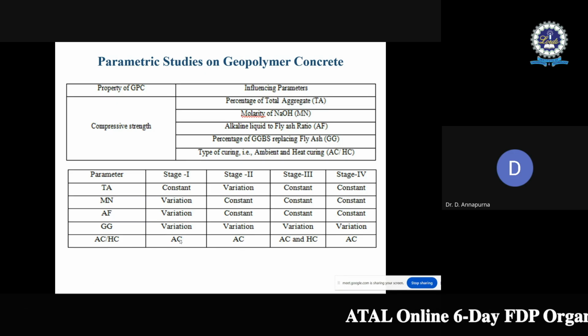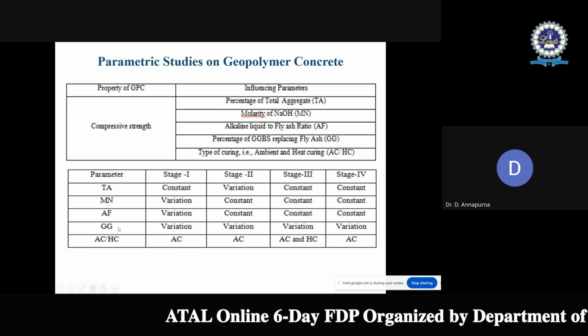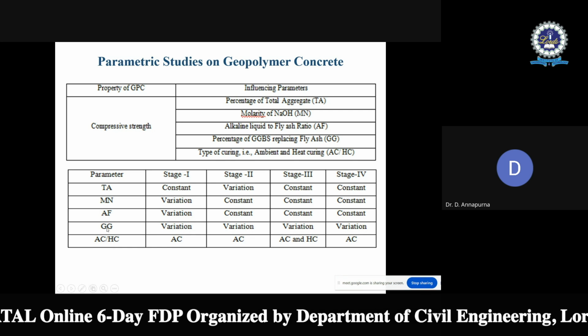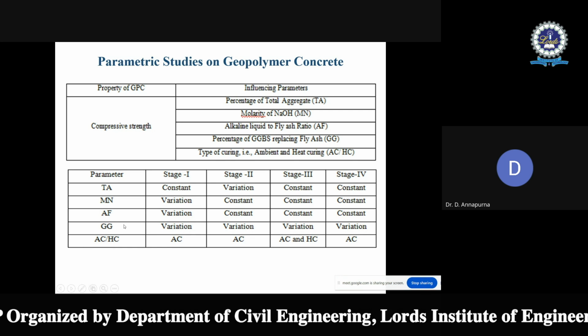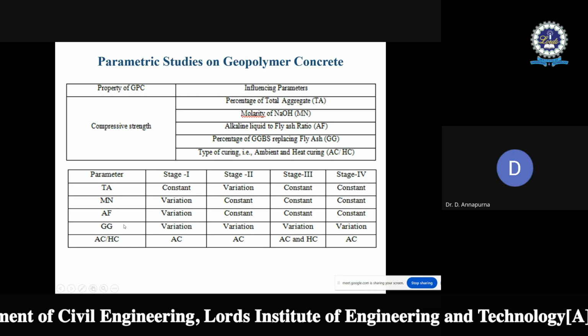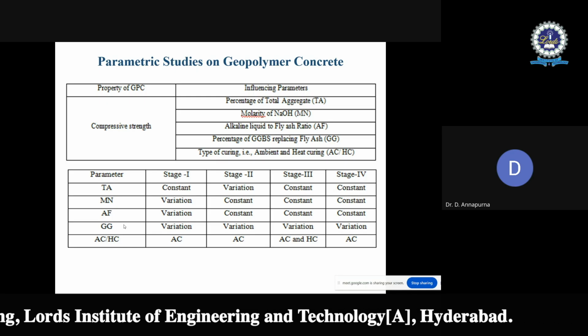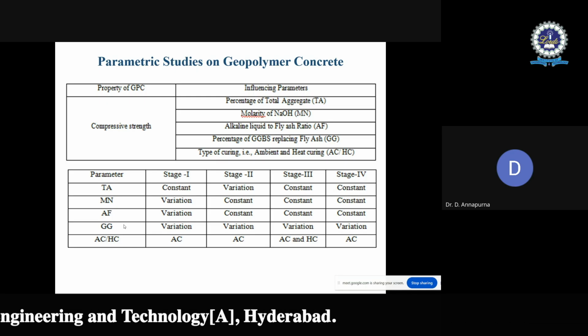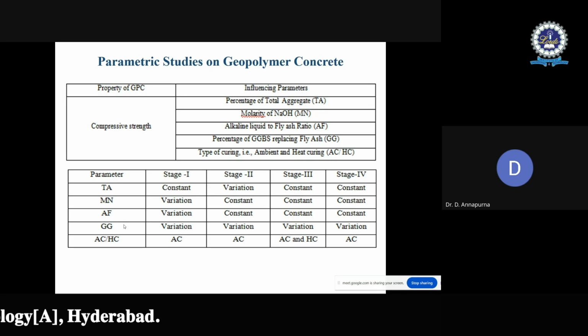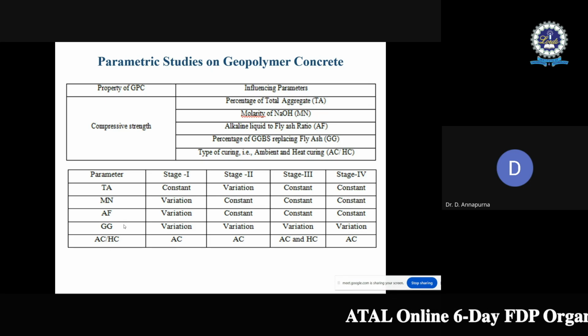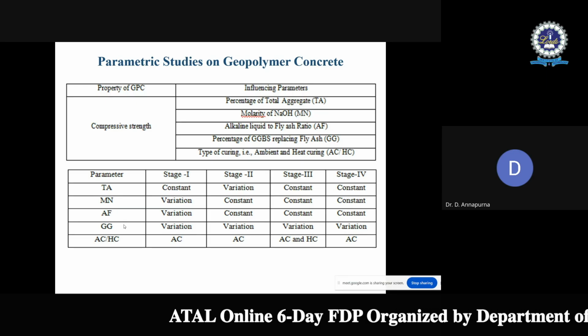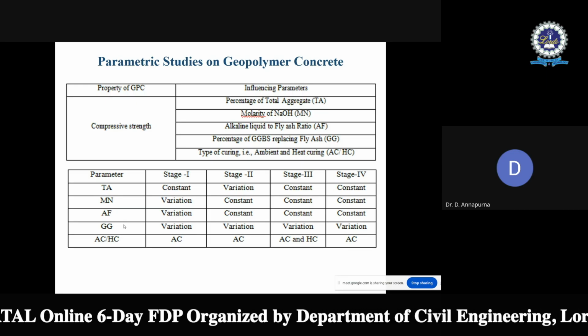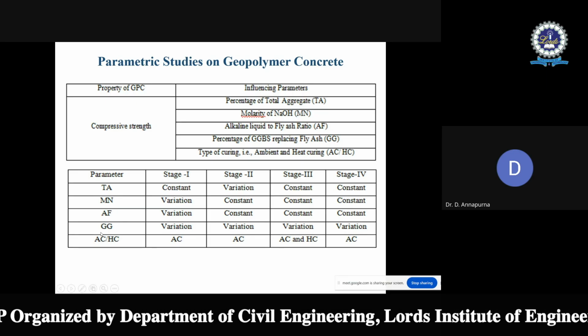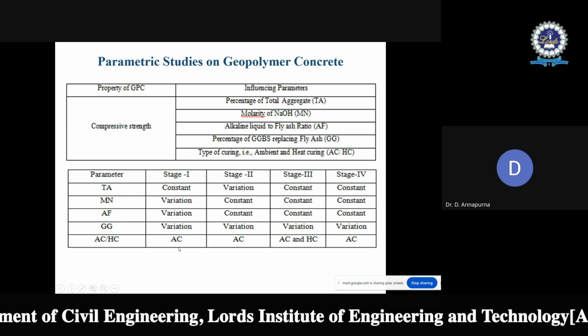Up to after 50% is also considered in the trial mix. Then it is identified that when the GGBS dosage is increased beyond 50%, its setting time is shortened to below 30 minutes. So its setting is too fast. And under practical conditions, we know that at least 30 minutes should be there to set. So that is the reason the amount of GGBS is curtailed up to 50%.